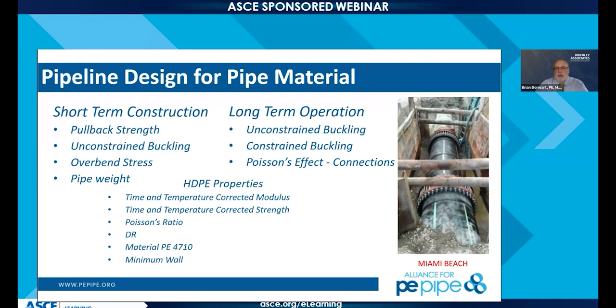These are just a couple of examples of trenchless installations. The only other one would be more of a slip lining or a bursting with HDPE. Again, you got your material around you when you're bursting. It's going to be left in the ground. We found that you can use PVC, but with HDPE, it takes a tremendous amount of abuse if you have a problem product, that host pipe that you're trying to burst. The HDPE comes through, even if it gets some scratches on it, it's just not a big deal, mainly because it's a gravity pipe, so scratches you don't really worry about, only in pressure pipes.